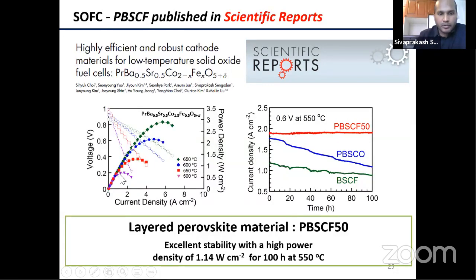At low temperature, about 500 degrees Celsius, it's about 0.5 watts power density.